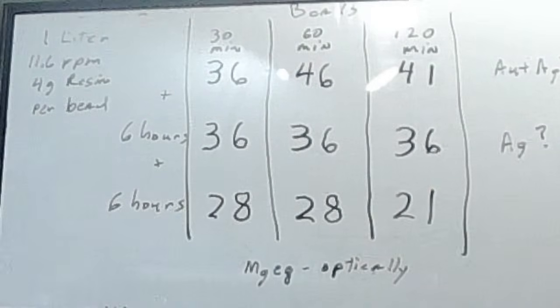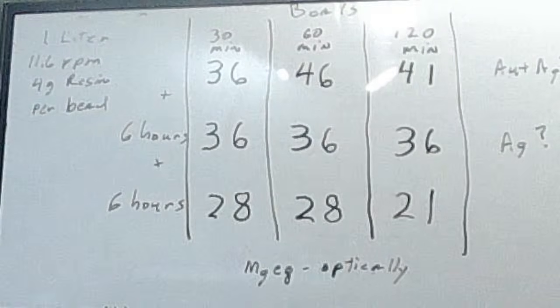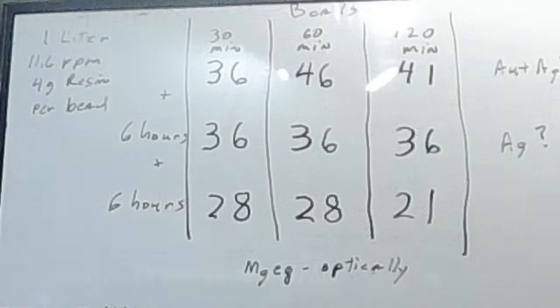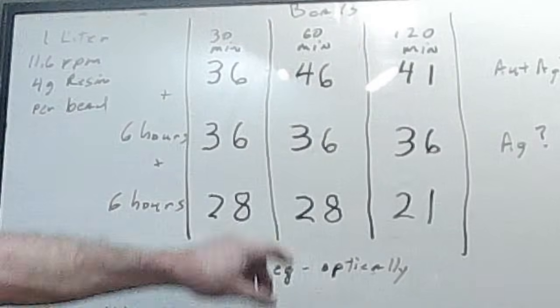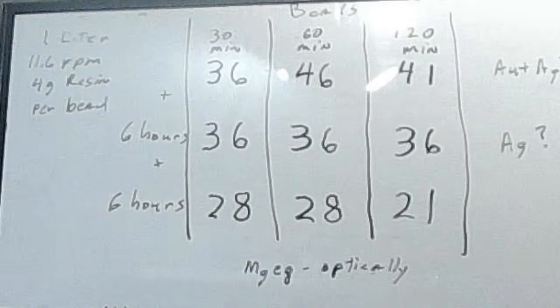tried to digest them. Now, if you have a bead, which I anticipated here from previous testing, that's around 50% gold, it's not going to dissolve in nitric. Okay? It just got way too much gold. Once you get to about a 4-to-1 ratio, it should dissolve readily in nitric acid. And in fact, this bead is still sitting there merrily in nitric acid, apparently untouched, whereas this dissolved in about 5 or 10 minutes, leaving a black residue, which is presumably finely divided gold. Okay?